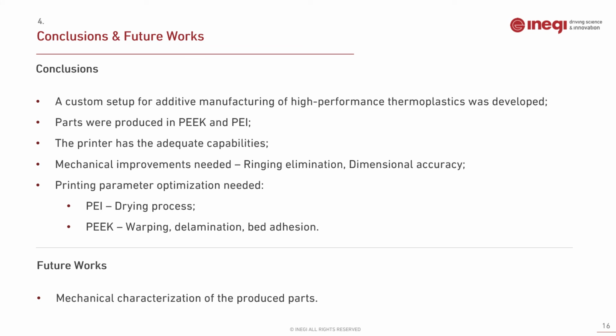Summing up, the conclusions taken from this work were the following. A custom setup for additive manufacturing of high-performance thermoplastics was developed. Parts were produced in both PEEK and PEI. The printer has the adequate capabilities for printing parts in both PEEK and PEI. Still, some mechanical improvements are needed. We had ringing in all the parts, which means we should try to reduce the vibrations in our printer. We also had consistent dimensional variation, which will be corrected by calibrating the axes.